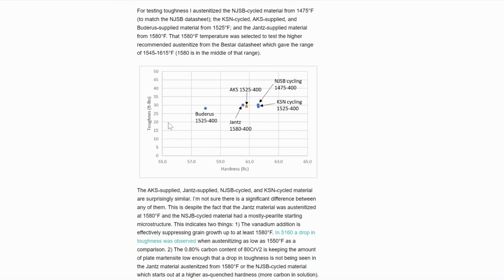But this can also affect the toughness. So here is my cycling using 1525 and a 400 degree temper. You get 30 foot-pounds in my test and 61.5 Rockwell or so. Whereas if you start with the Buderus material with the same heat treatment, you get only 58 Rockwell, and the toughness is no better, even though it's significantly softer. So you would have to austenitize hotter or temper lower to get the same hardness. And maybe the toughness goes down at that point.